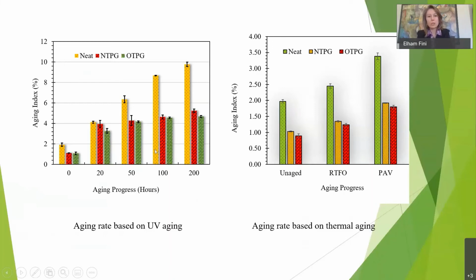So the yellow is the road that we have today, the asphalt that we use in Arizona today. And you can see how badly it aged within this number of hours. So 200 hours, let's say, under sun. Of course, this is a lab measure. So 200 hours in the UV aging exposure. The yellow is the current road. That's how it aged. And the other two, green and red, are when we added the plastic, with the green being the oil-treated plastic.